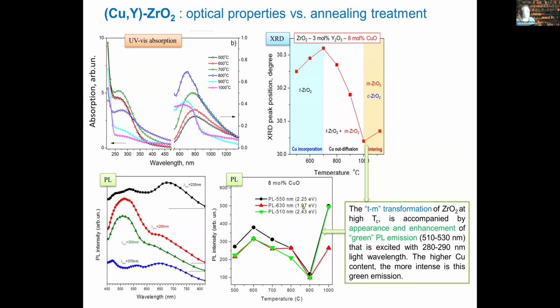If we compare the photoluminescence, we discovered that when we got formation of monoclinic zirconium oxide, we had very bright luminescence in a specific green range, and it became higher with higher copper content, and higher with greater transformation from tetragonal to monoclinic phase. The combination of optical characterization allowed us to suppose that we can use such doping, or properties of copper, to see where we are, so whether we have monoclinic phase formation or not. And measurement of luminescence spectra and electron paramagnetic resonance definitely tell us how to control it.